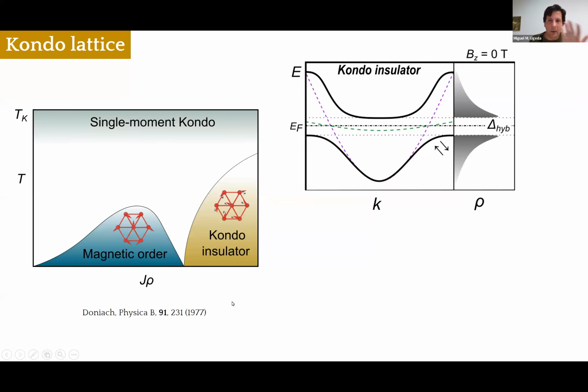So here I show you a picture of the Kondo insulator in the band structure. The origin of the Kondo insulator regime is the interaction between the flat band due to the localized magnetic moments, which is depicted here in green, and the conduction band electrons, which is this dispersive band. So the hybridization between these two bands leads to new spin-degenerate bands, both above the Fermi level and below the Fermi level, creating what is called a hybridization gap here, close to the Fermi level.